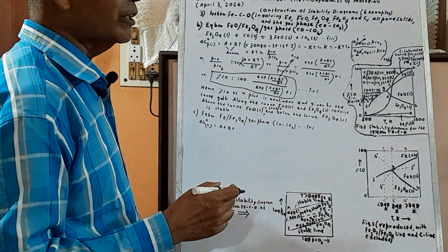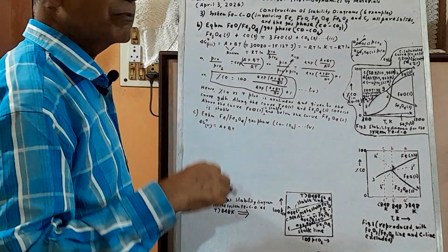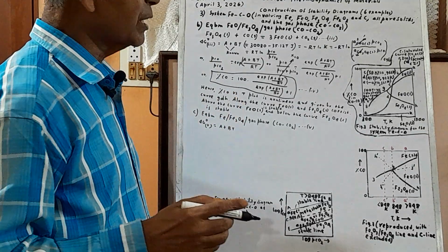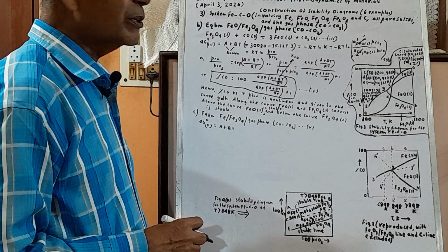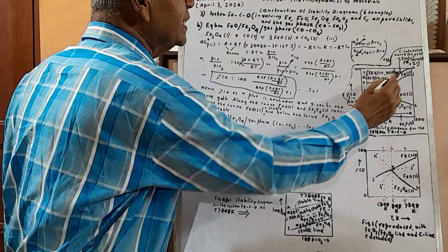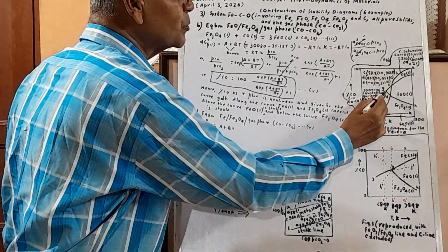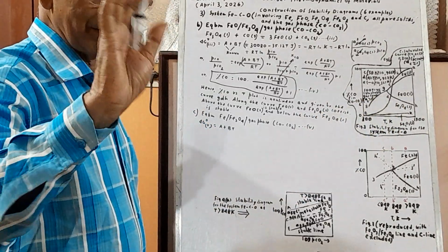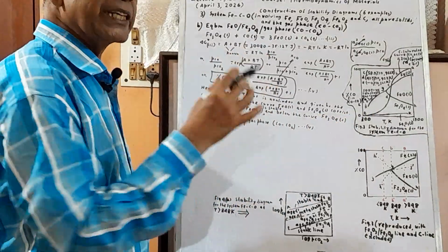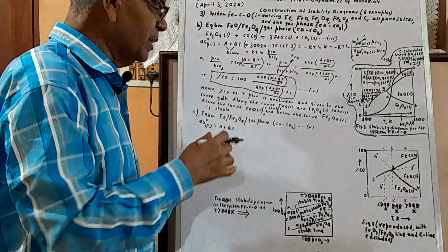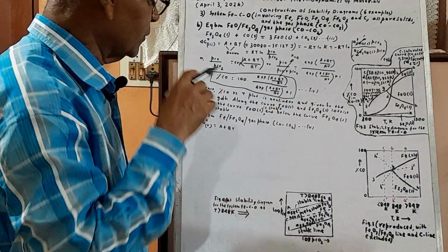So you should note this. Remember this figure, always remember, this is a very important figure in direct reduction, in iron making, very, very important: the iron, carbon, oxygen equilibrium diagram. You should note that the slope is ascending type for all of 1, 2, 3. The fourth one is descending type. The carbon curve I have not said anything about yet, this is the carbon A, B, C, D. We have already read it a number of times, but it will be included here also. This is a different type of curve. That is a different issue.